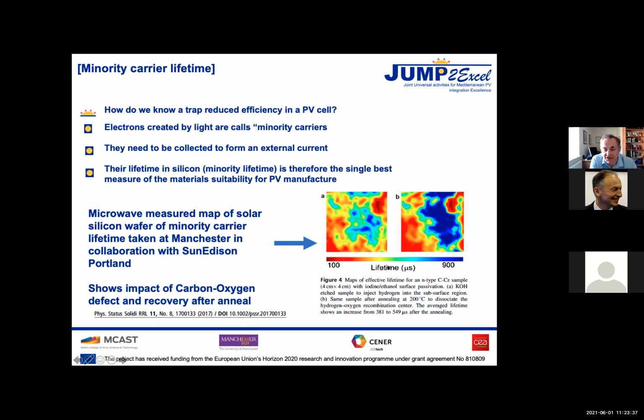And then after annealing at 200 degrees C, we predicted that we can destroy this complex by annealing at 200 degrees C, and it's been destroyed. And so they changed their process to put in this extra step, which would ensure the destruction after the firing process. It's called an extra anneal. So they basically waited at 200 degrees C for a bit longer than they needed to. And that was effective at destroying this defect and restoring the long lifetimes. Okay, that was published in this paper here.